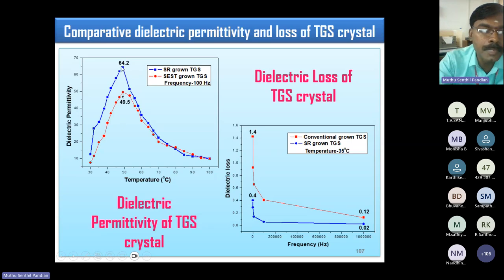The Curie point of this TGS, triglycine sulfate, is 49 degrees. Below this 49 degrees, the crystal belongs to the ferroelectric phase. Above 49 degrees, the crystal belongs to the paraelectric phase. And we have successfully grown the crystal in both its ferro and para phases, and we compare the physical properties and the crystalline perfection of the ferroelectric and paraelectric phase grown TGS single crystal.